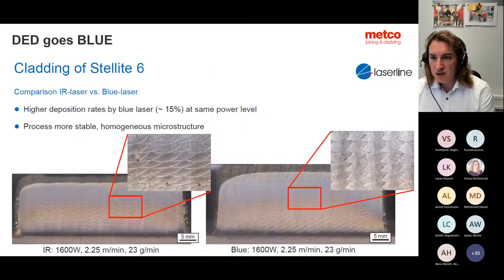What was a surprise? If you work with conventional materials like cobalt, nickel alloys, or even iron alloys, also there, first results indicate that using the same process parameters with a blue energy source, you get higher deposition rates, around 15% to 20% increased deposition rates at the same power level. You get a more stable process, and you can also better interact with your materials in the melting bath, and as a result you get less porosity compared to infrared. Blue lasers are still quite expensive, but the advantages you get, for example working with copper-based materials, depending on your application and requirements, already have a certain advantage.